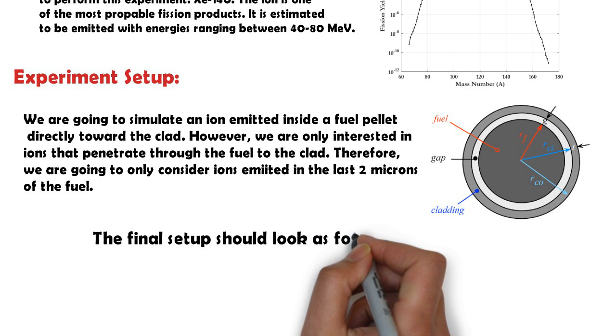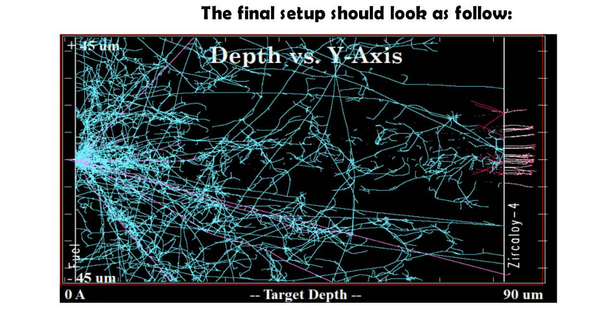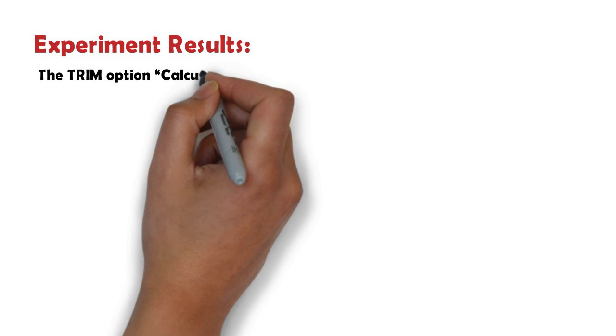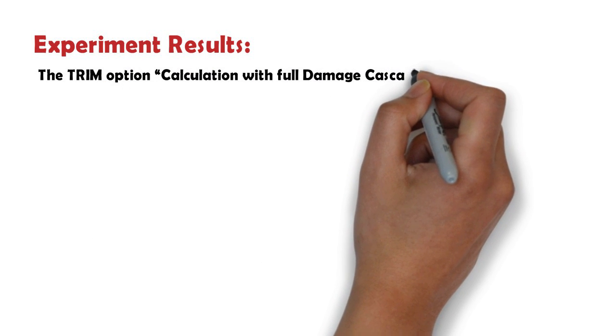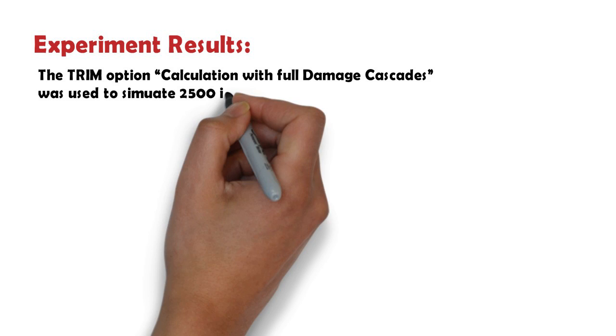The final setup should look as follows. Ions will be randomly emitted anywhere on the first layer of the target, which is 2 micrometers of uranium dioxide. Then it will go through a second layer of 80 micrometers of helium gas before finally hitting a 10 micrometer layer of clad material. The TRIM option calculation with full damage cascades was used to simulate 2500 ions, and the following results were obtained.